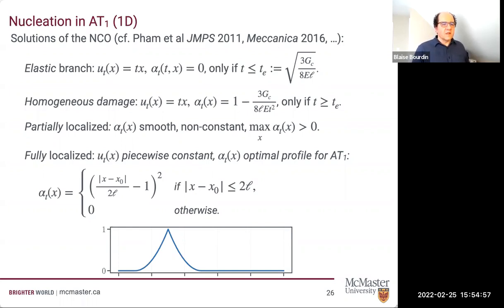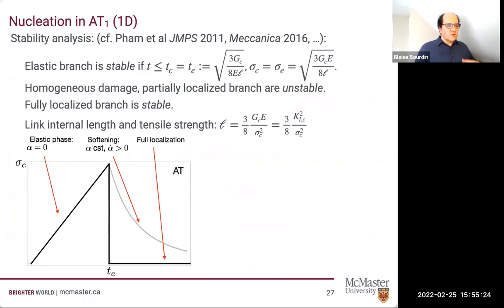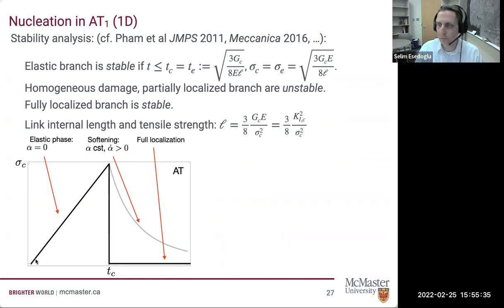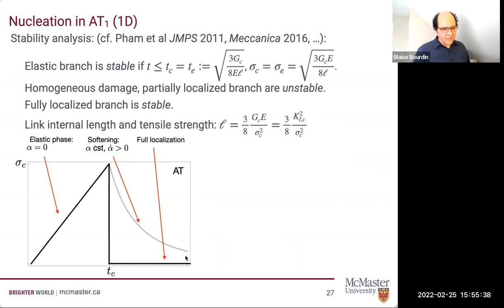What's missing in most papers, and it's done very beautifully in this string of papers by Corrado Maurini, Kim Pham, Jean-Jacques Marigo, and so on, is the stability analysis. And again, I wanted to get to this one because it's pretty important. Because we have a variational theory and not something based on criticality, we have another criterion to decide on which of these branches we want, and we want one that is stable. And so you can do a second order stability analysis and show that the only stable types of solution are elastic or completely fractured. So in 1D, what you have is either a linear response or a crack.